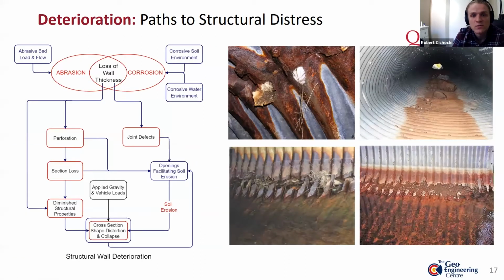So here's a chart summarizing what I learned about how abrasion and corrosion can cause structural distress and concerns. Generally, abrasion and corrosion will result in the loss of wall thickness, as well as perforations, and lead to diminished structural properties. When we apply our vehicle loads and gravity loads, we can probably expect some sort of cross-section shape distortions and potentially collapse. And if that wasn't bad enough, section loss and perforation also leads to openings facilitating soil erosion. So we also open up an opportunity for another deterioration mechanism to occur.